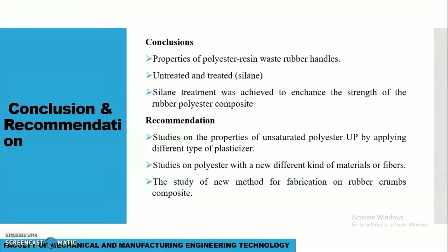Okay, for the conclusion and recommendation, this research focuses mainly on changes in the properties of polyester resin with rubber glove, untreated and treated with silane. There are two main parts that have been determined and studied here, which is to study the difference between untreated and silane-treated waste rubber crumb composite. Silane treatment was used to enhance the strength of the rubber polyester composite, and 6% weight percentage of silane is the best silane treatment, because the objective is to determine the effect of this treatment on the rubber polyester composite for both tensile and flexural as well.